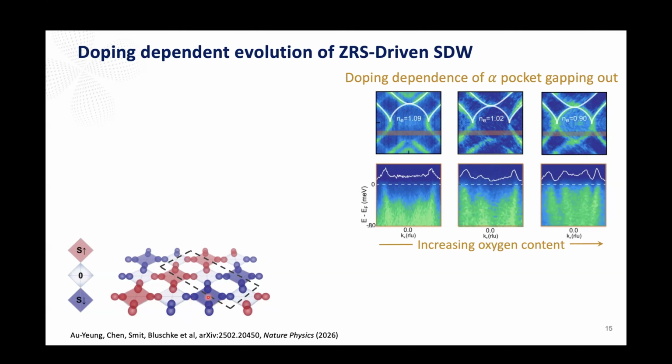The nickel is in the middle, and this is a net negative magnetic moment in this plaquette, and the red one is the net positive magnetic moment in the plaquette. If we arrange the oxygen orbitals like this, it will give you a very natural up, zero, down, zero order of the spin density wave, which is what was reported.